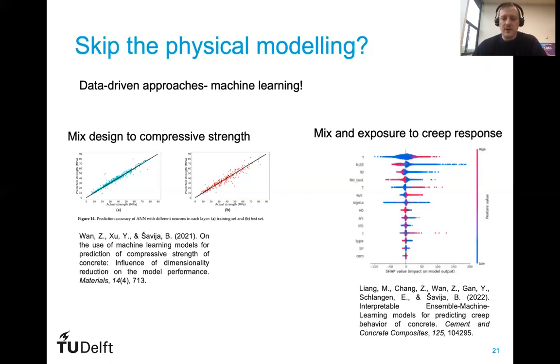We also developed ensemble machine learning models to relate the mix design and different exposure conditions, time of loading, temperature, age, relative humidity, and so on, to the creep response. And what is interesting about this approach is that we can not only relate the input parameters to the output, but we can also use the models to see how much impact each of the input parameters has on the output. For example, here we see that time of loading has a very large positive influence on the creep. So let's say the earlier we load, the higher the creep. And we can do that.